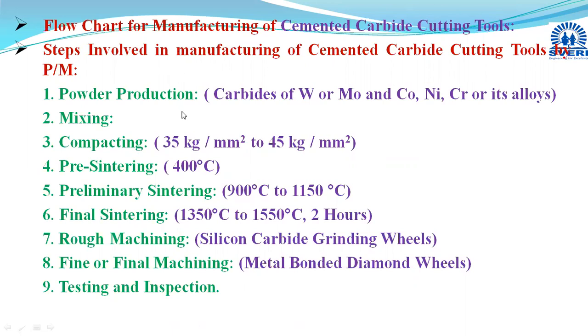Okay, now for this cemented carbide cutting tool, you will find that the number of stages is more, but you will find that there is sintering here. Three ways of sintering are here depending on temperature zones. Okay, pre-sintering, preliminary sintering, then final sintering, and machining is done in two different ways. That's why I have highlighted here two steps of machining and fine or final machining. Okay, that's why you will find that stages are more. Okay, actually only 5-6 stages will be there.